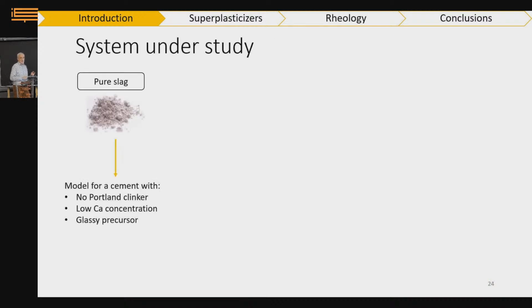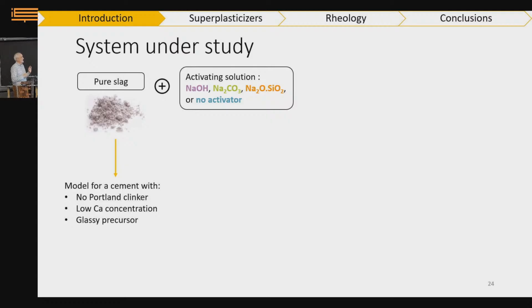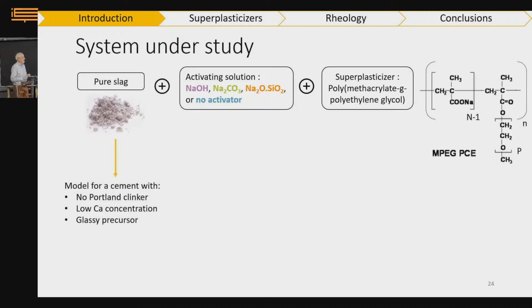So we simplify the system with respect to a true cement paste. We just use slag, okay? So no cement, no Portland cement. It's not a blend, just pure slag. We activate with hydroxide or carbonate, and we'll see later on what goes on when we also activate with silicates, or we don't activate and we compare the behavior of those systems, okay? In presence of a very common superplasticizer, which is a polymethacrylate backbone grafted by a polyethylene oxide, by a PEG that is methyl terminated. So it's a very commonly used polymer by the industry and sold in relatively high amounts.